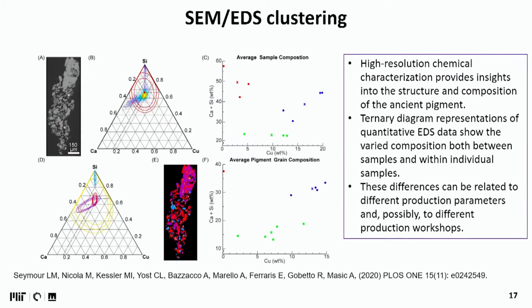And what we were able to do is, again, map on the micron scale, imaging the chemical differences in different samples. Here, high-resolution chemical characterization provides indeed insights into the structure and composition of ancient pigment. Ternary diagrams, representations of quantitative EDS data, show different compositions between samples, and these differences can be related, of course, to the differences in different production workshops.